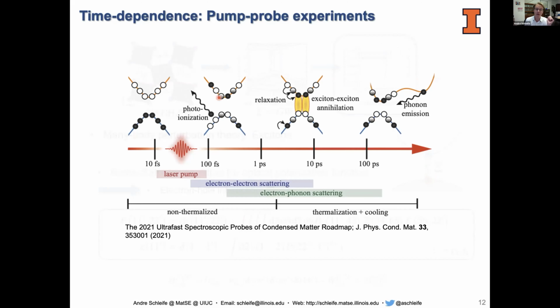However, that's just the starting point of a whole cascade of processes that then follow in the material. You can see this in this cartoon picture. These electrons are not in equilibrium at all, there's not even a temperature in the early stages, they will relax. There is electron-electron scattering and electron-phonon scattering, which usually occur on different timescales. Usually the electrons first become a Fermi distribution, the holes become a Fermi distribution with a temperature, and eventually they will also recombine. This time dependence we would like to describe, because people access it in experiment.